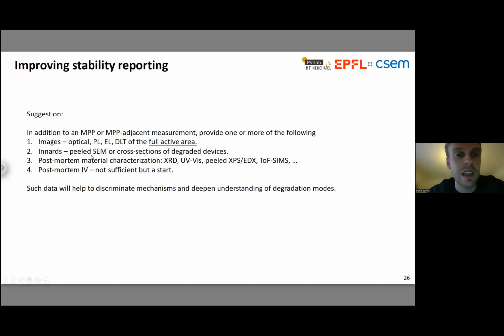It would also be nice to do post-mortem testing in which we look at the innards of our degraded devices. So looking at, for example, the formation of voids, as I showed very briefly in one of my slides, looking at cross sections, and also doing post-mortem material characterization to see what's happening in the degraded areas. If that were to become more standard practice, it would be really helpful to deepen the understanding of different degradation modes, to see whether we are all actually addressing the same sorts of issues. And then we can start to think about strategies for moving forward. So that's that.